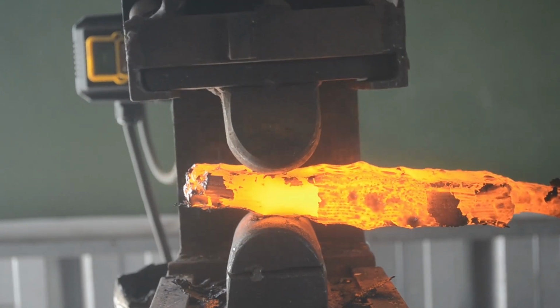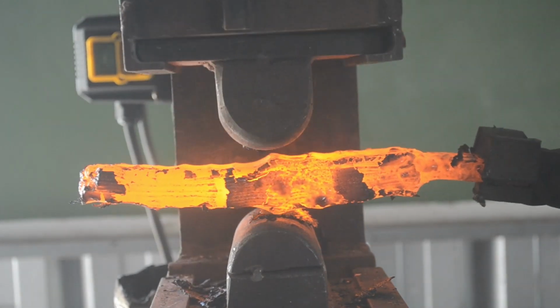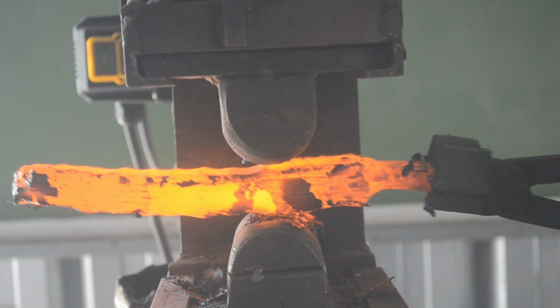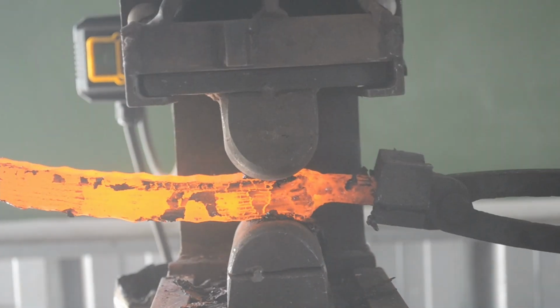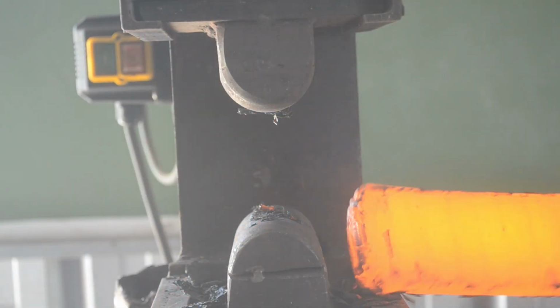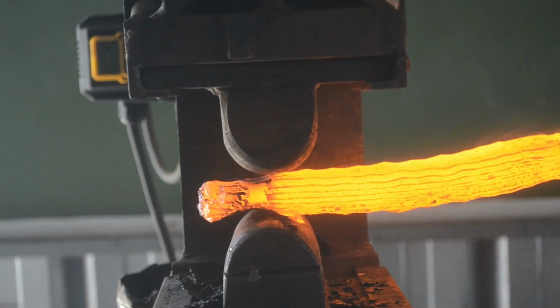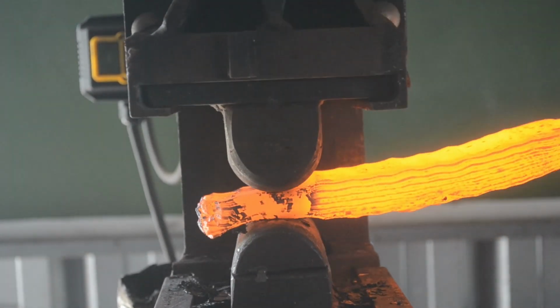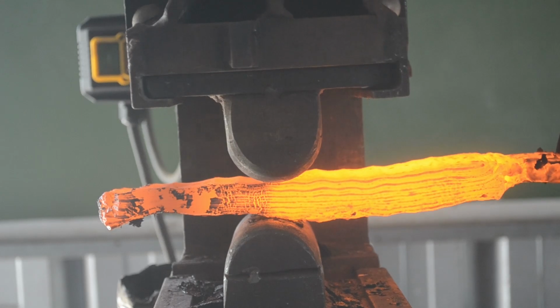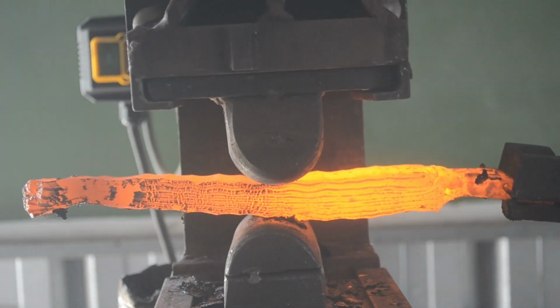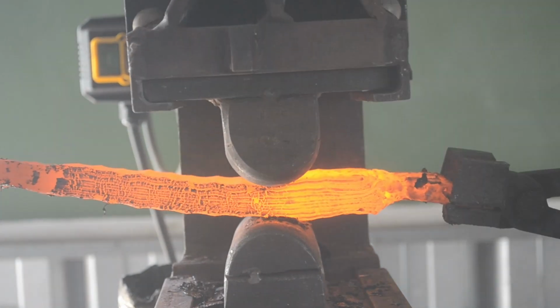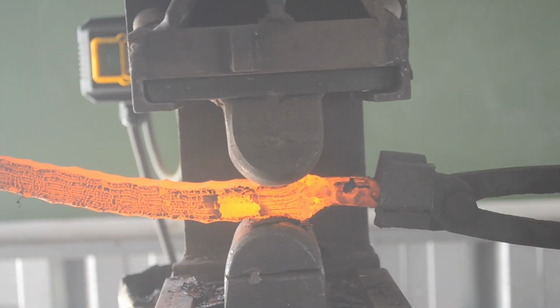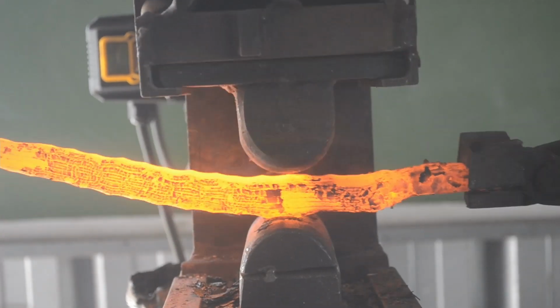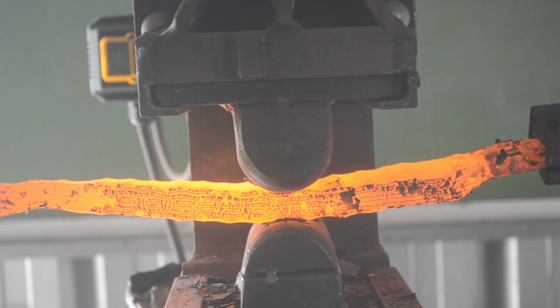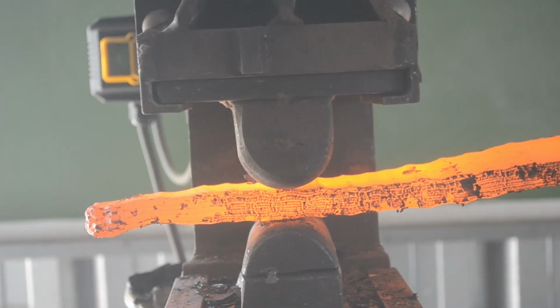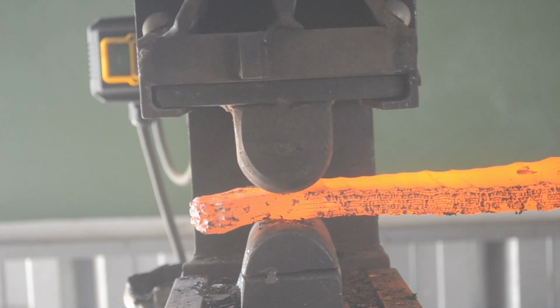And that was probably because I used a dissimilar metal electrode to weld my Damascus billet handle on, and that's a stainless based billet, and if there's any gaps in the laminate, then the oxide that comes off of that specific electrode gets between the layers, and because stainless oxides do not weld even with flux, it can destroy your billet weld. I was lucky in that I managed to get rid of the delam with some more flux and a little bit more heat.